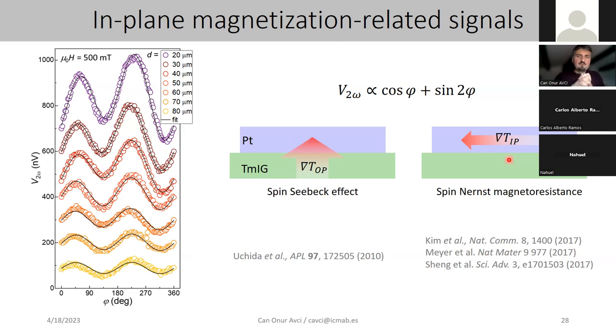Another effect that we found is due to the spin Nernst magnetoresistance, because as I explained before, it acts like the spin Nernst magnetoresistance, but instead of an in-plane charge current, now we have an in-plane thermal current, so the temperature gradient is the driving force. And then you get a sine 2 phi behavior as well. So this signal was a composition of cosine phi plus sine 2 phi, which we understand as the spin-Seebeck effect and the spin Nernst magnetoresistance. These two effects were not new to us, but it was a way to confirm that we have these two gradients operating together.